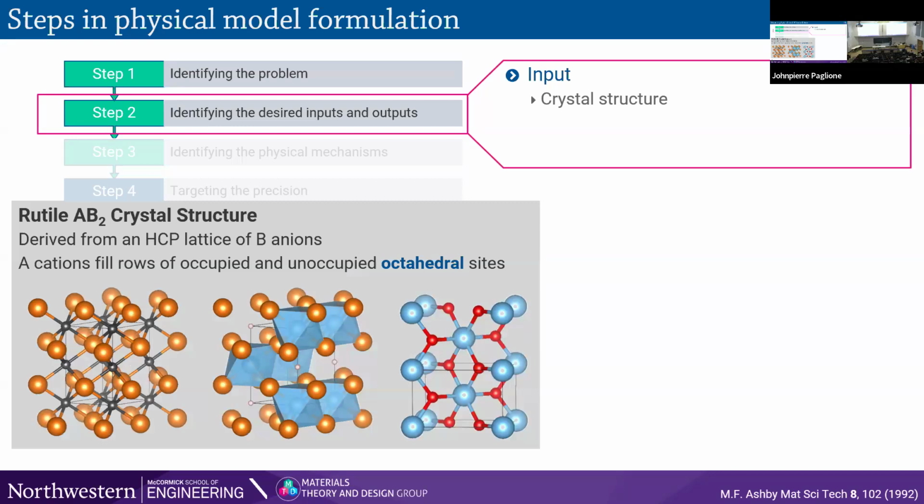And again, because this is the altermagnetism workshop, or novel and emergent magnetic phases, I've taken the rutile structure as a relevant phase of interest. So the rutile structure has an AB2 composition, and you can describe the structure kind of like we heard this morning for rock salts, as a close-packed FCC structure. Rutile is derived from a cubic or a hexagonal close packing of anions.